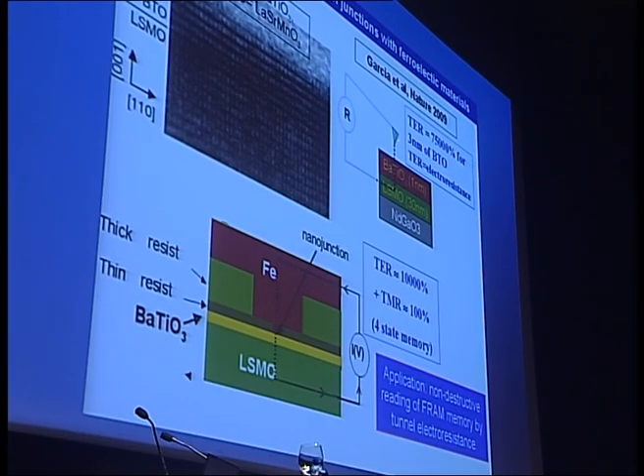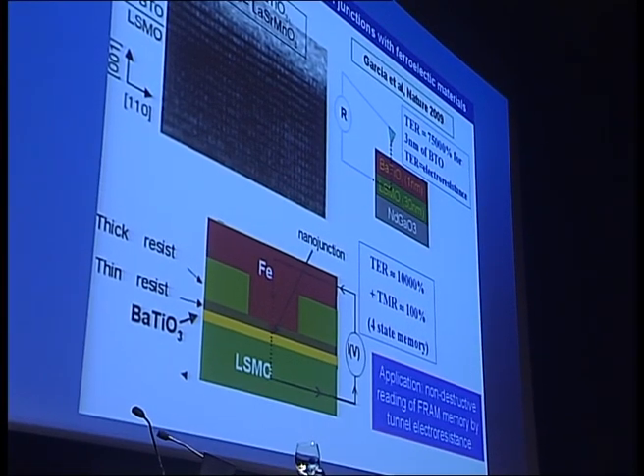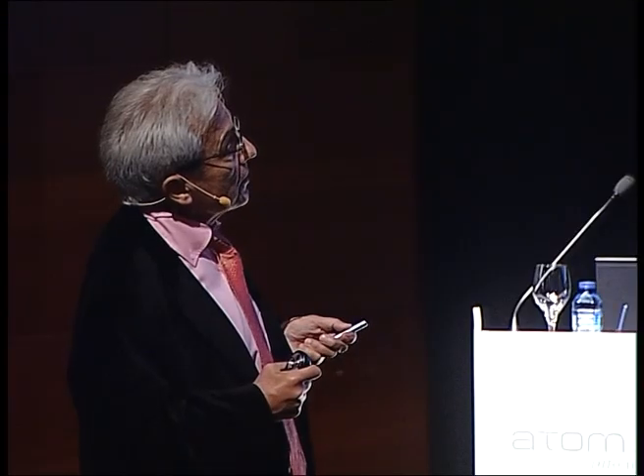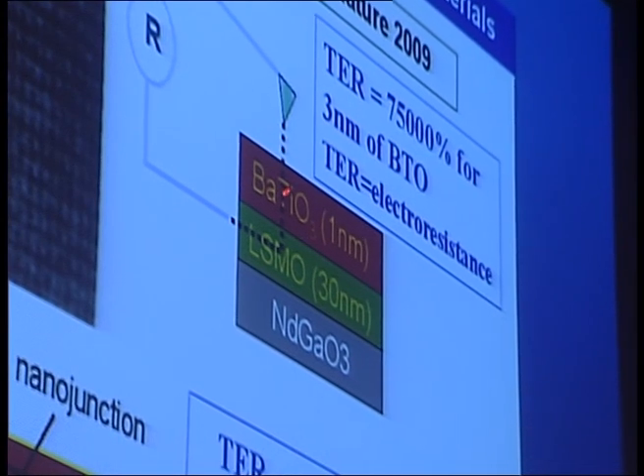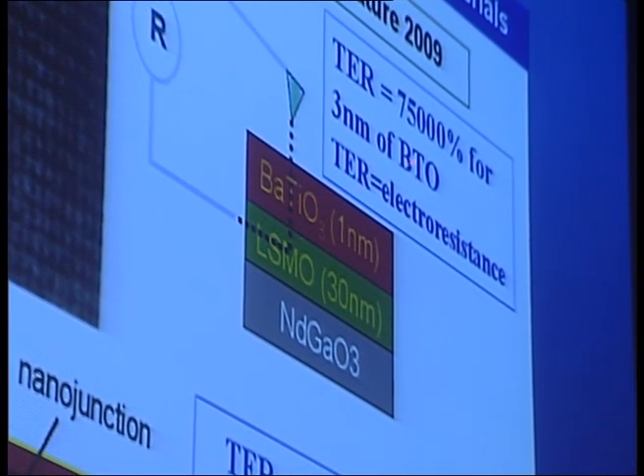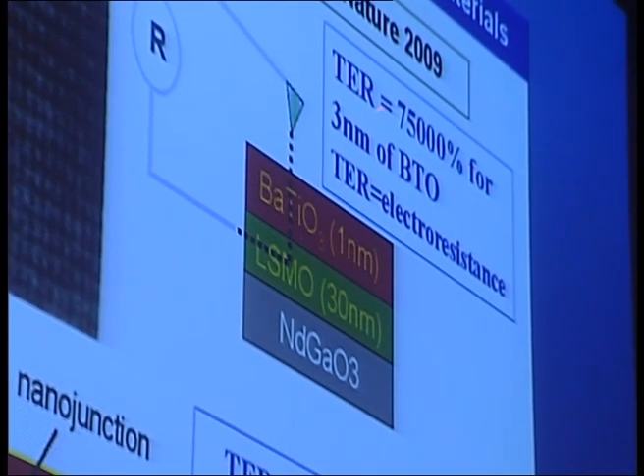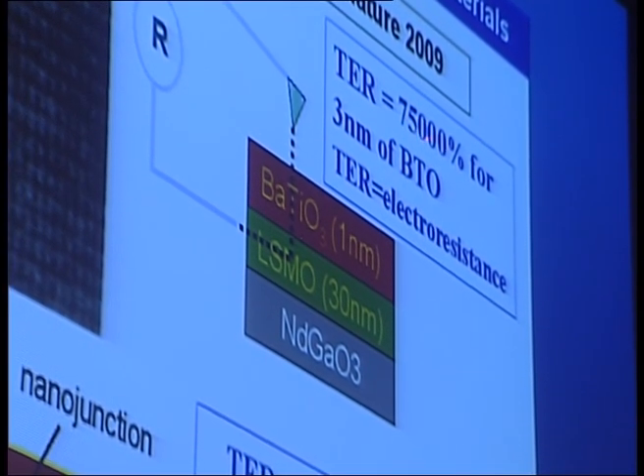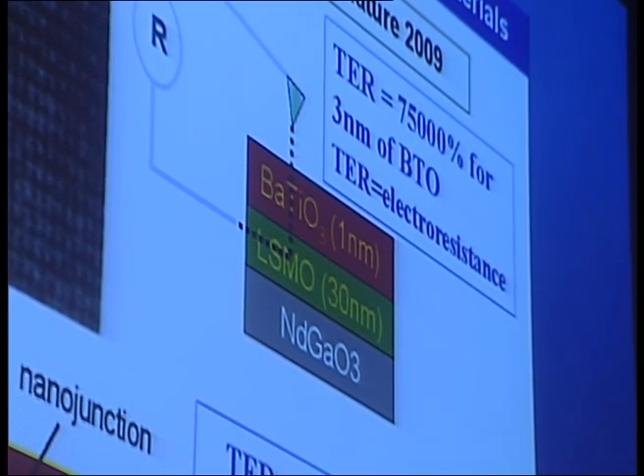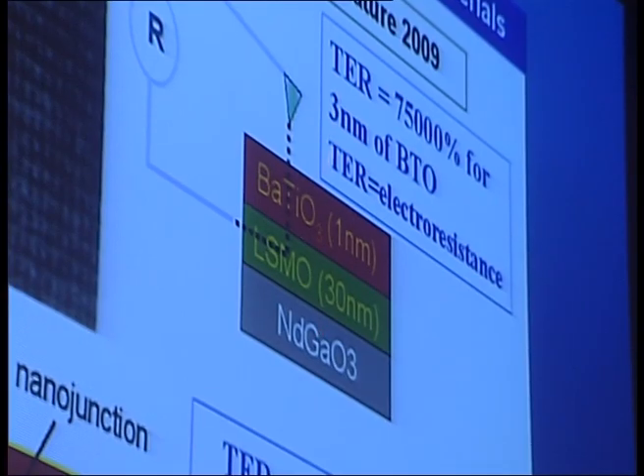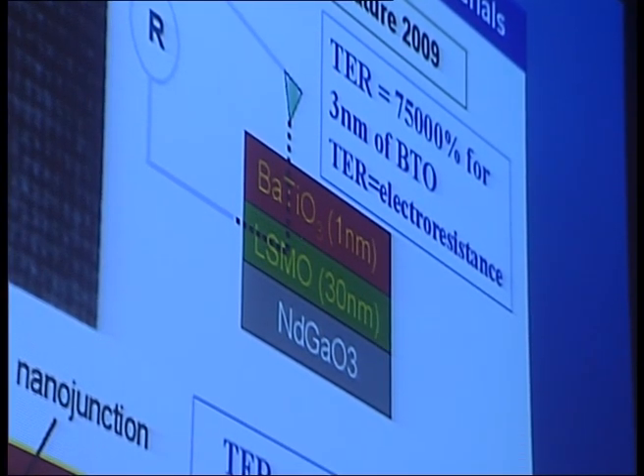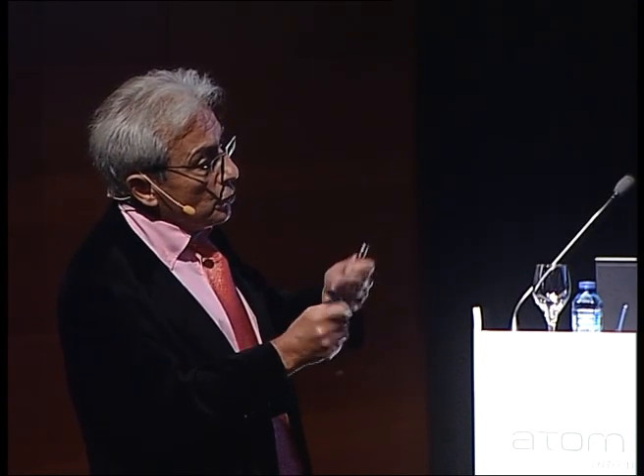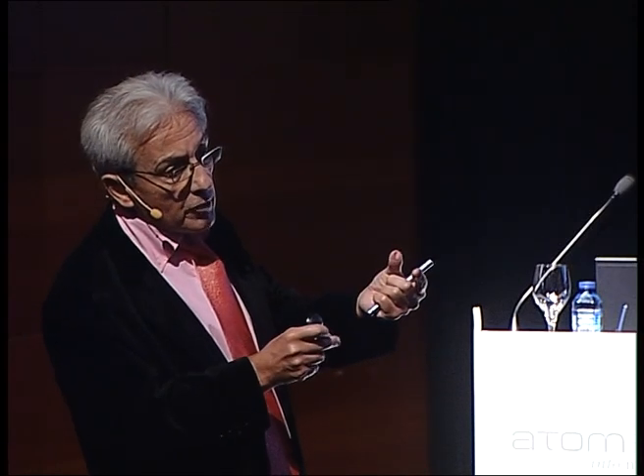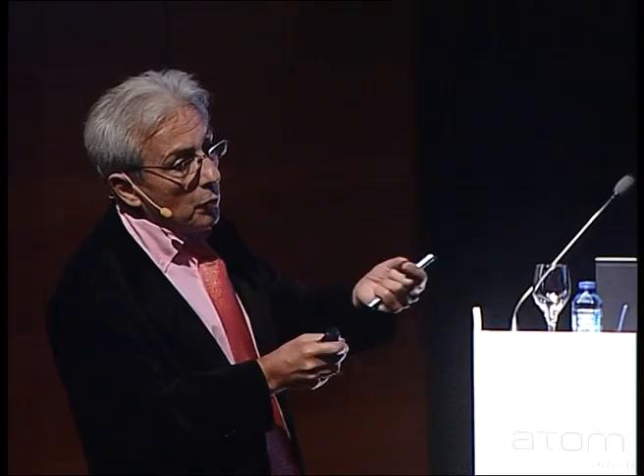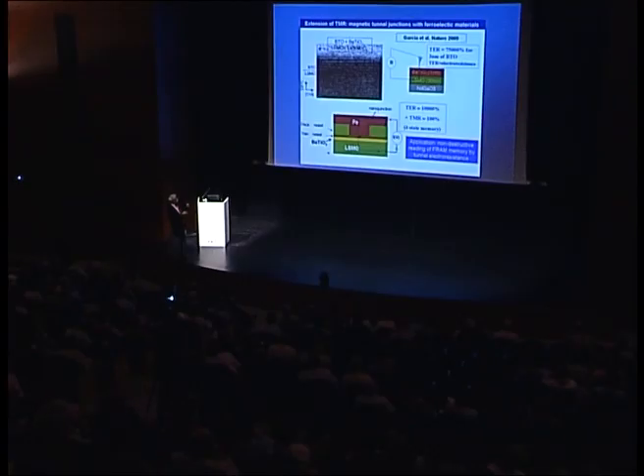And the good surprise was to see that what we call the electroresistance, the difference of the tunnel resistance depending on the orientation of the ferroelectric polarization, was very large. The TER, tunneling electroresistance, of 75,000 percent. That means an increase by almost a factor of 1,000 between the two orientations of the polarization of the ferroelectric barrier. This is because the ferroelectricity, depending on the orientation, changes the distribution of electrons at the interface, and the distribution at the interface is very important for the tunneling. It determines the bonding of the electron wave function in the electrodes and in the material.